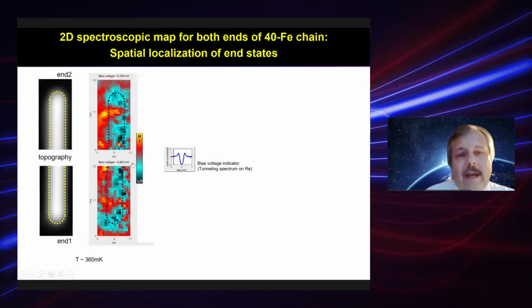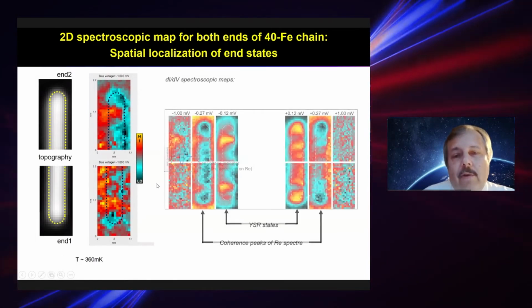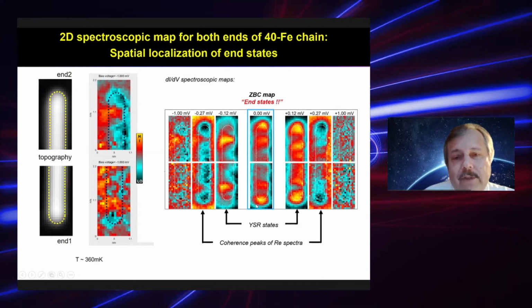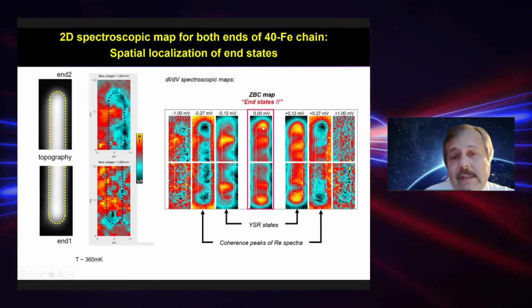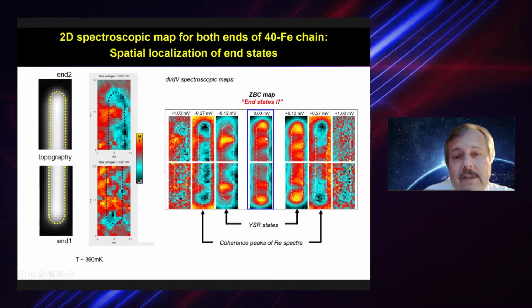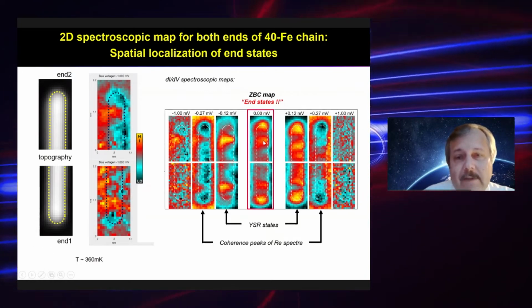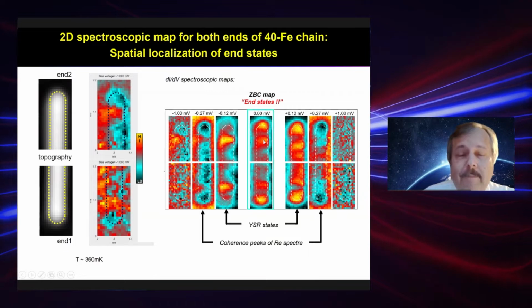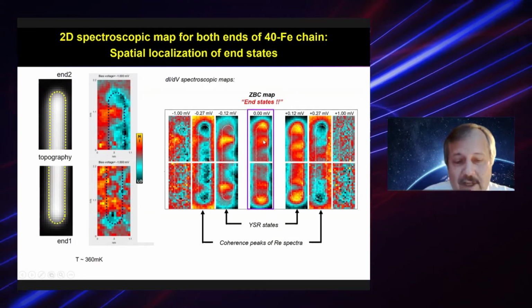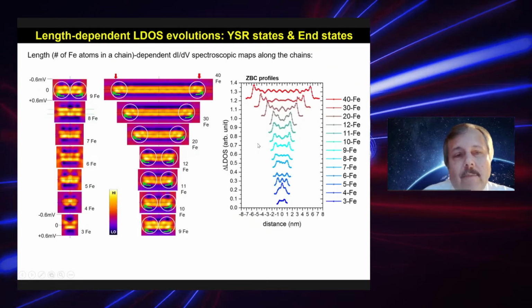And then, of course, we are again outside of the superconducting energy gap. So clearly at zero energy, we observe these very pronounced zero energy modes, but we can also see that there is some overlap with the finite energy states, the trivial Shiba states. This is a problem which I'm coming back to in just a few minutes. But first, let me analyze this data in more detail.